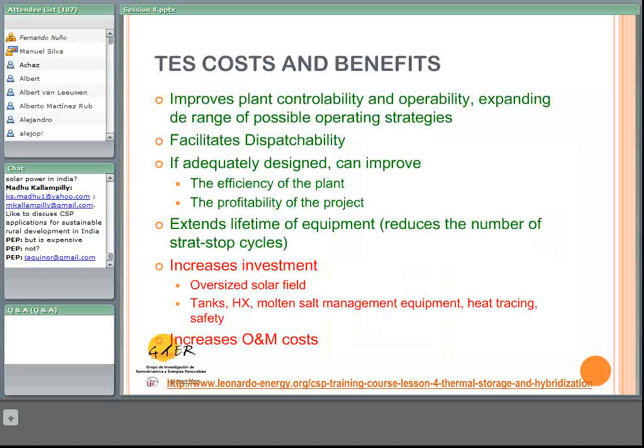Normally, when we operate from the thermal storage, the efficiency of the turbine, of the power cycle, decreases a little bit, because normally the operation is at reduced conditions, at lower temperature than if we operate directly from the heat transfer fluid. But this loss of efficiency is normally compensated by the fact that the plant can operate for more time at high load, and there are fewer starts and stops of the plant. In this sense, because it reduces the number of start-stop cycles, the use of a thermal storage system normally extends the lifetime of equipment.